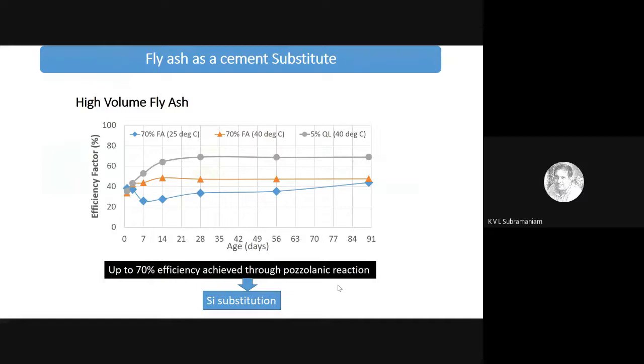Now, I just wanted to show you in this graph the efficiency factor when you start increasing the replacement level. So when we started increasing the replacement level of fly ash, at 70% you see the efficiency drops off, and the maximum efficiency that we were able to get in the system was about 70%.